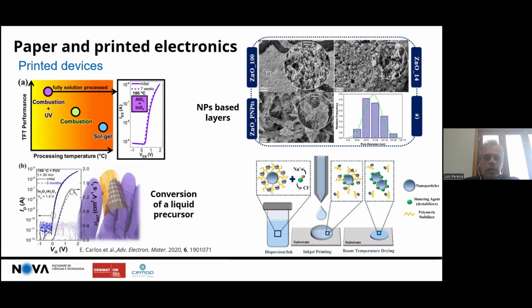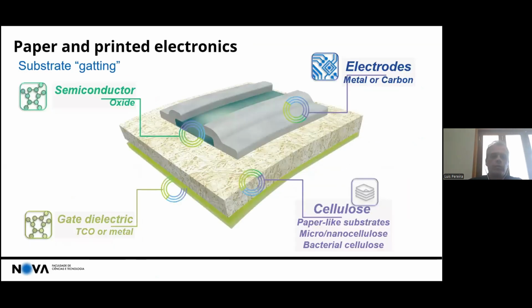There is also something that we already tried and works nicely, but it's not easy to implement in a roll-to-roll process, that is electrical field sintering. You can also use some binders that help you to get this percolation. So there are many options. And it's a good approach because you can deposit the particles and dry them very fast in a roll-to-roll machine, in seconds in a convection air furnace, and it's perfectly compatible with the printing process.